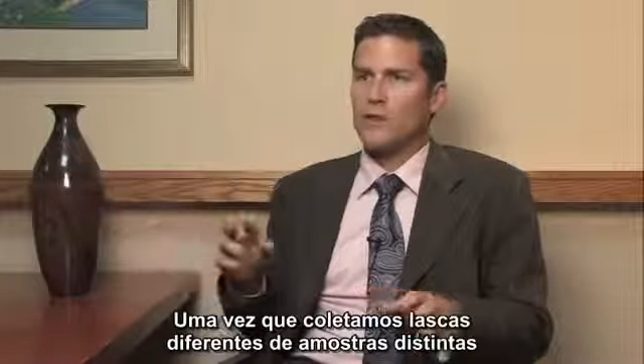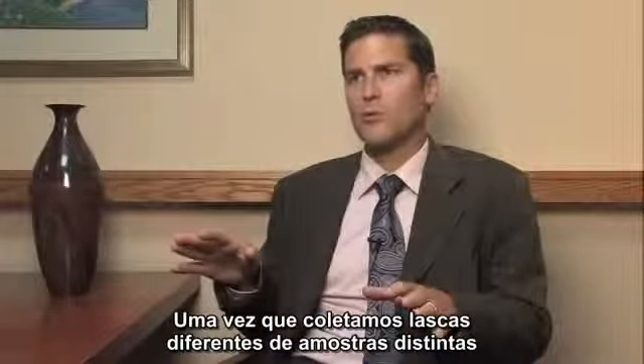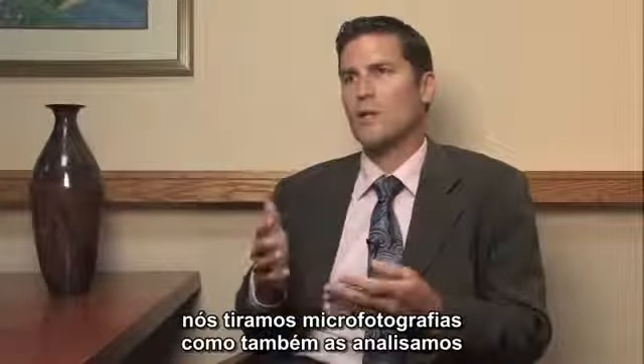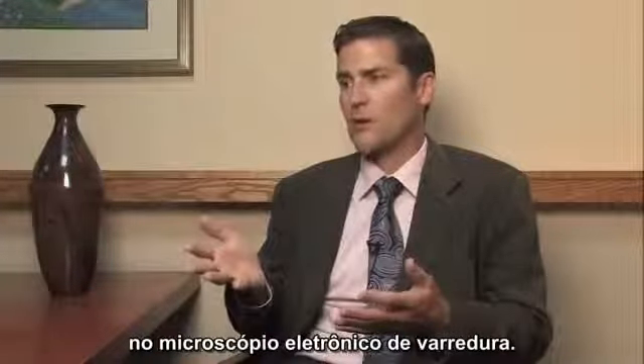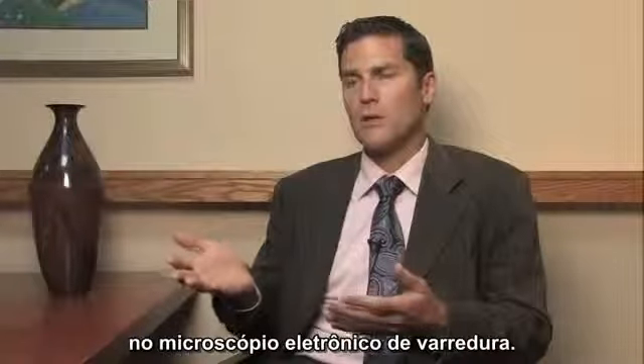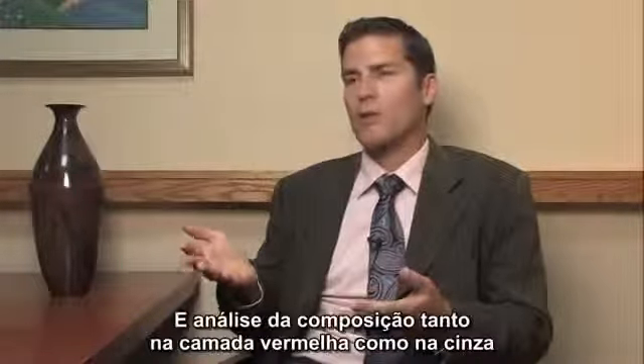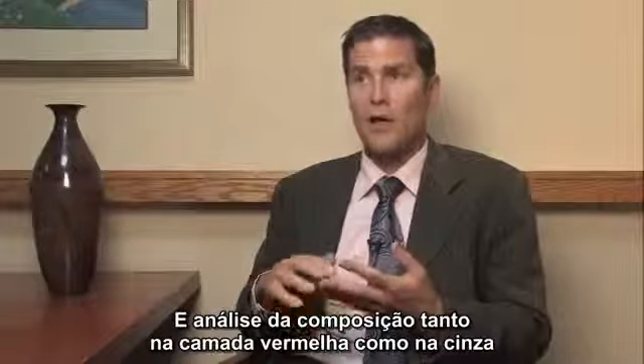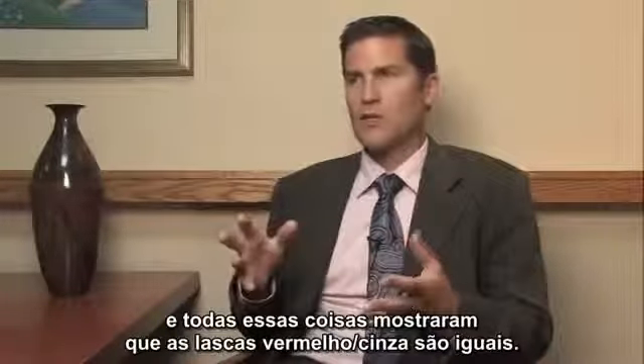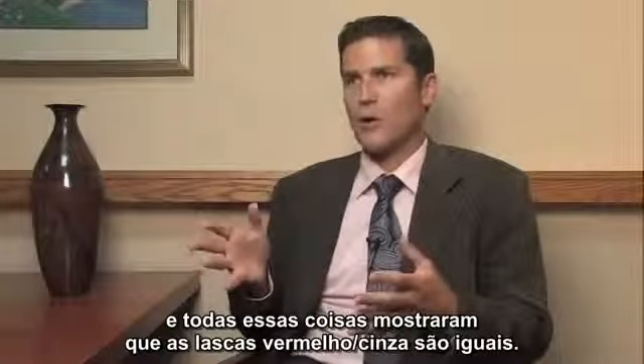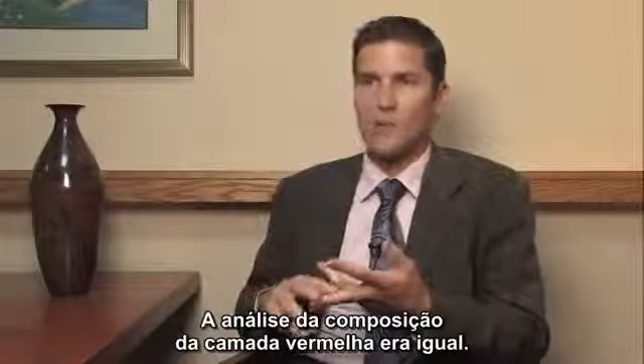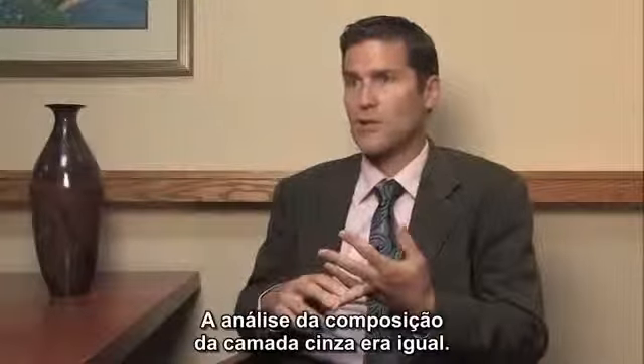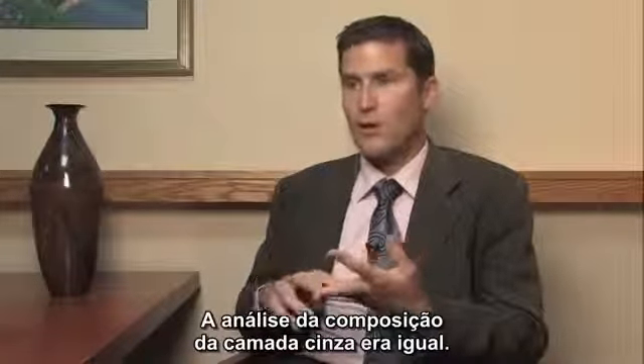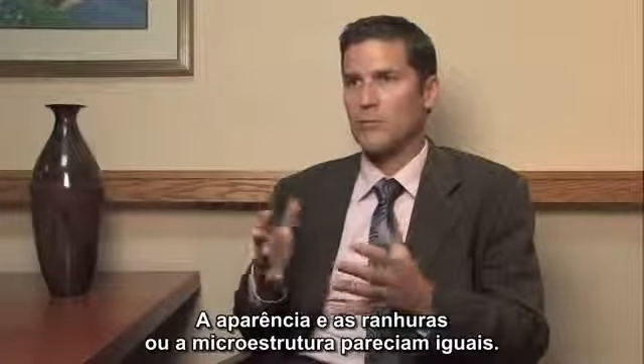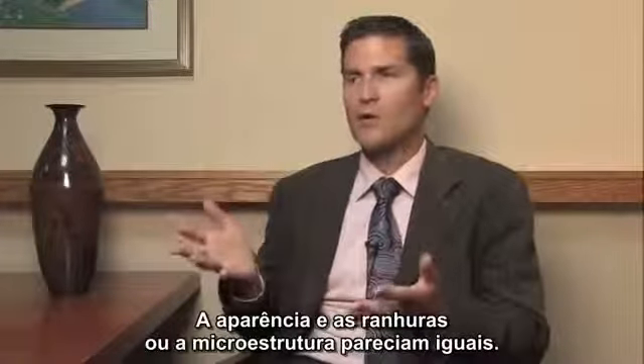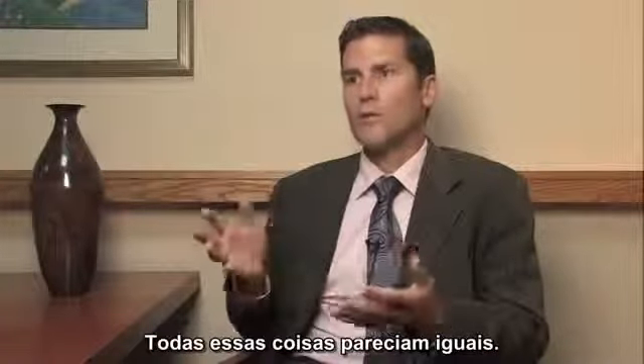So once we collected different chips from the different samples, we then took photomicrographs as well as looking at them in the scanning electron microscope, and then compositional analysis of both the red layer and the gray layer. And all of these things showed that these red-gray chips are the same. The compositional analysis of the red layer was the same. The compositional analysis of the gray layer was the same. Their appearance and cleavage habit or microstructure appeared the same. All of those things appeared the same.